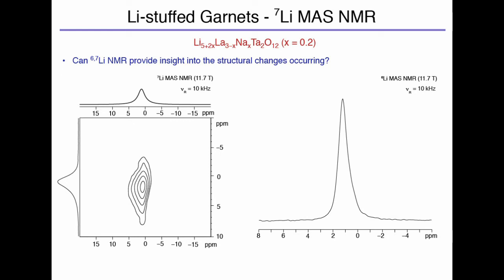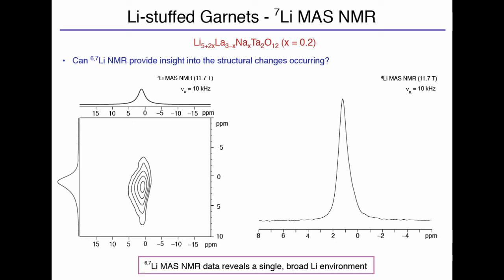And we tend to not do this first because it's a complicated experiment. It takes a much longer period of time. But we can do it if we think there's scope for doing it, i.e. if it's going to tell us more. But unfortunately, in this particular case, it gave us just a single broad resonance again and was largely uninformative. So both seem to give us just a single lithium site, even though we know we have an octahedral and a tetrahedral site.